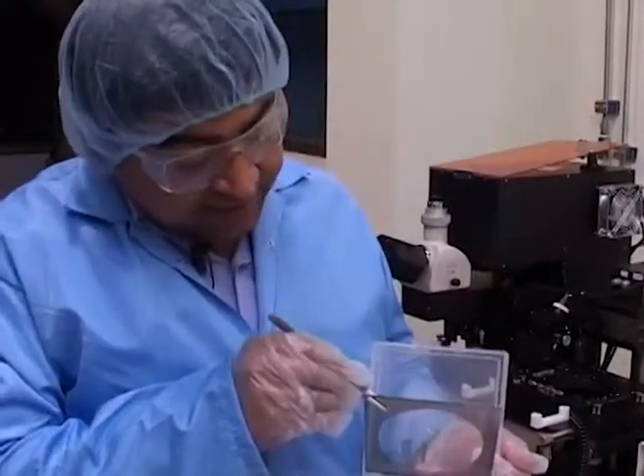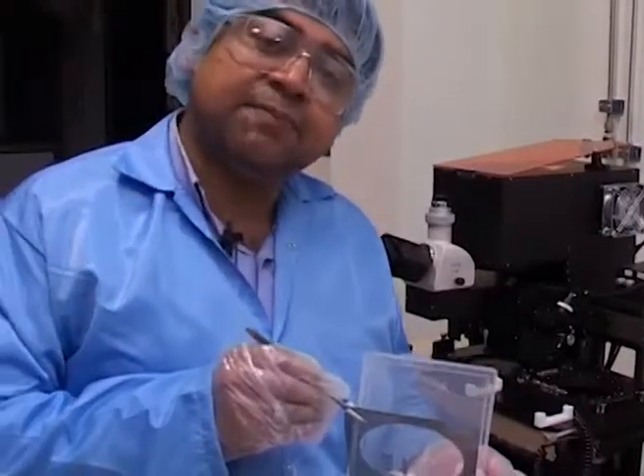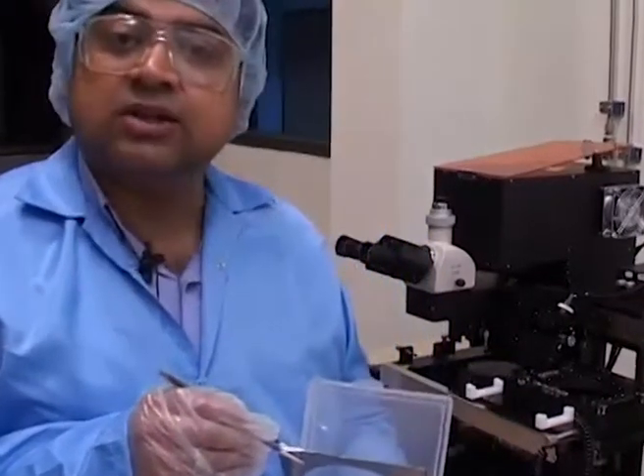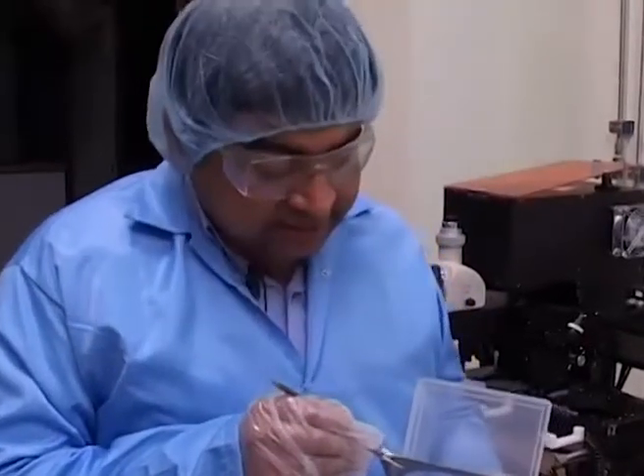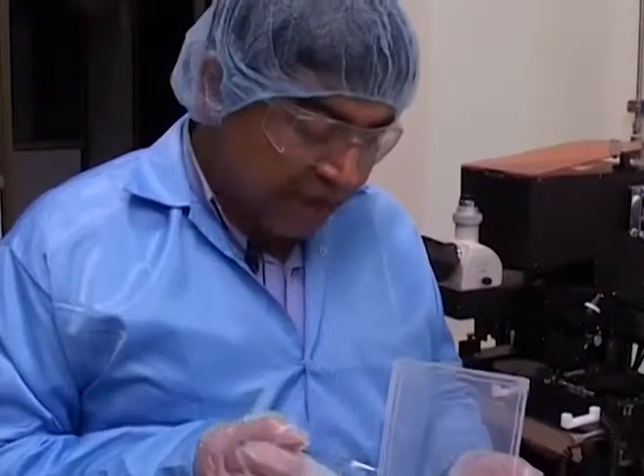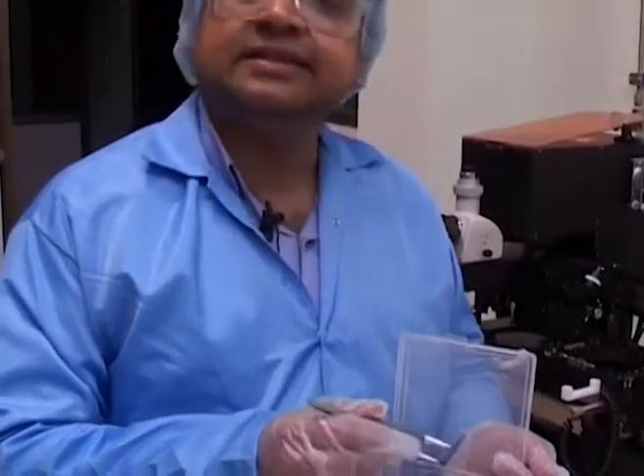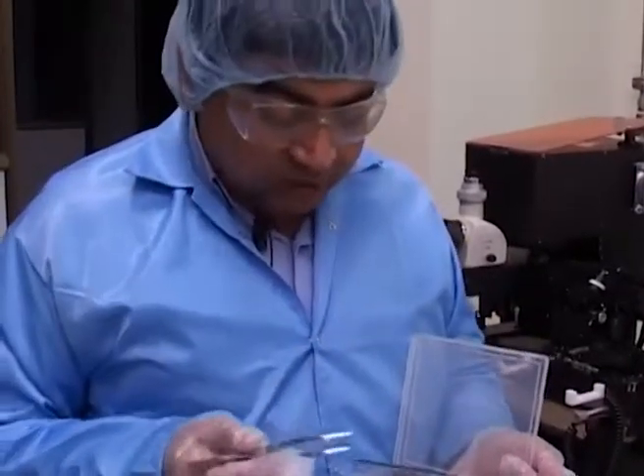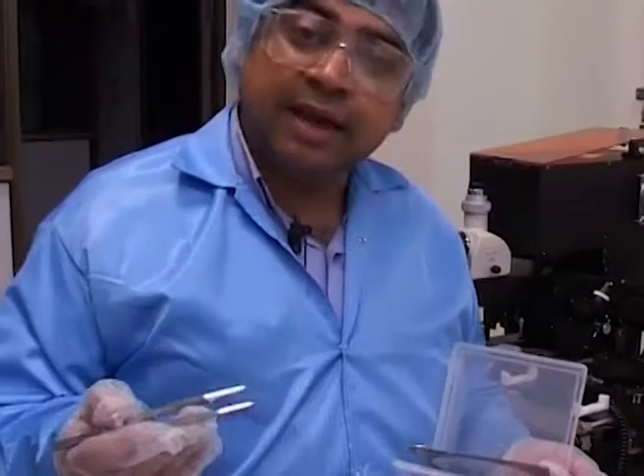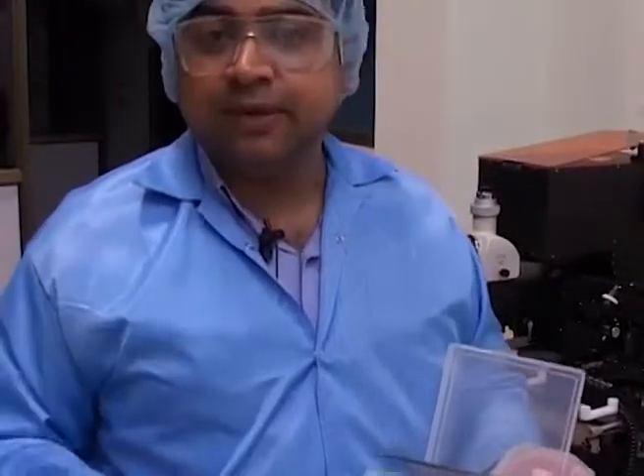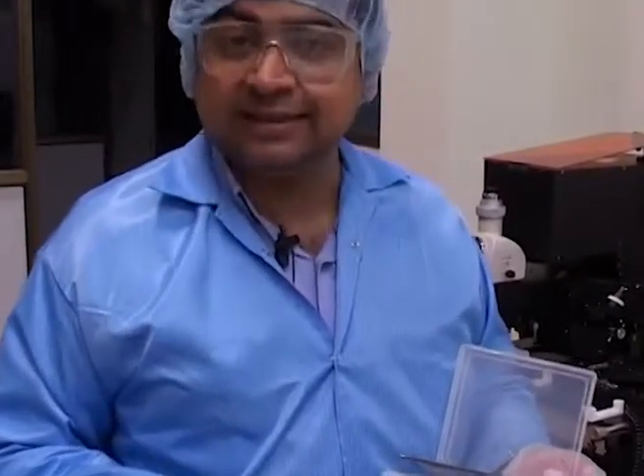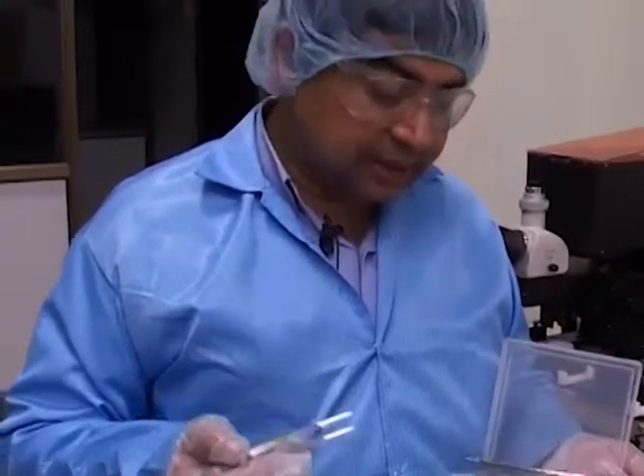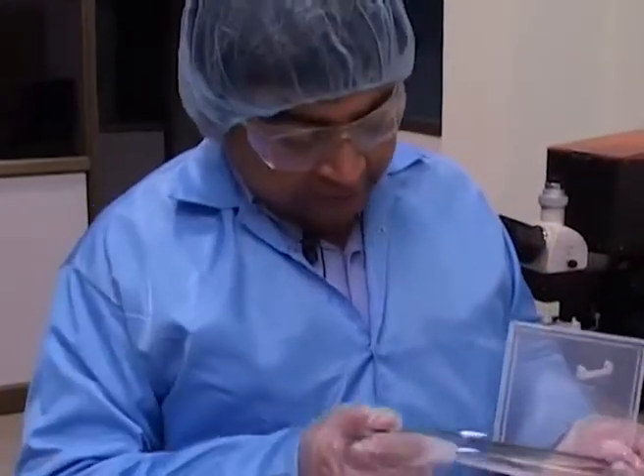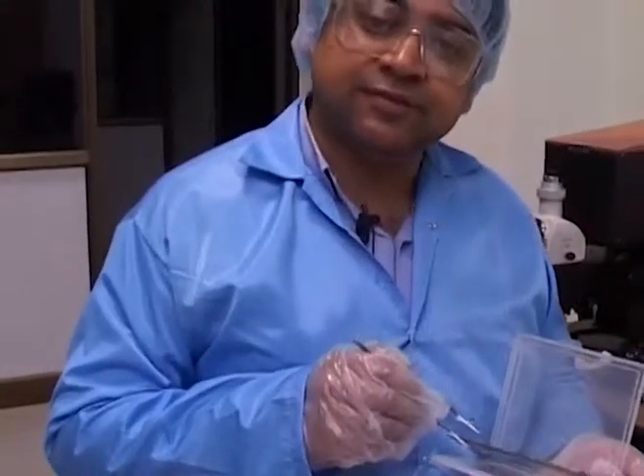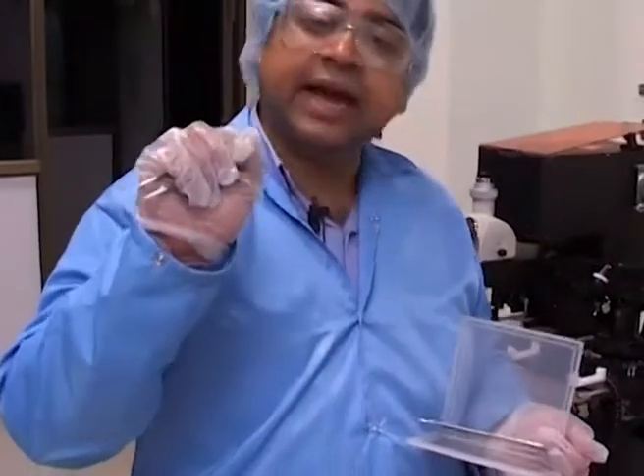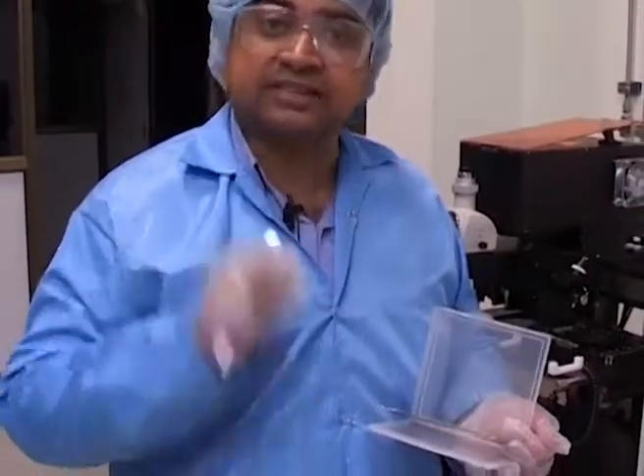If you see the thickness of the mask, this is made in a glass plate which is close to 900 microns or so thick. And so therefore, it is a very good idea to have the metallized surface in proximity to the coated wafer. 0.9 mm or 900 microns is good enough for a beam of light to get hugely diffracted. And so if we were to do it the other way around, with the glass side sitting on top of the wafer, the features that we would be looking at would be much larger in size because of diffraction effects.